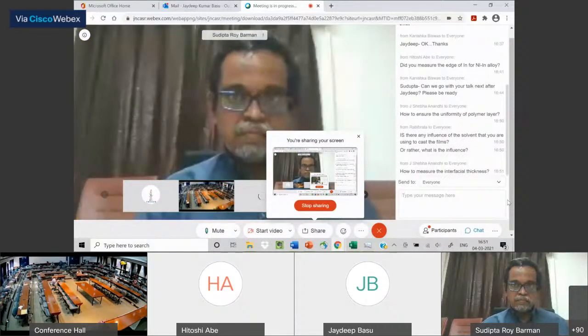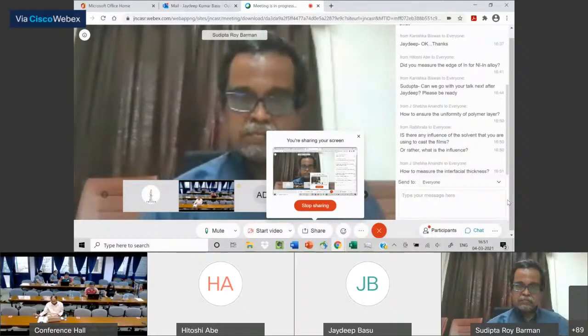Basically you wash out the film. When you wash the film, you see that there is a remaining layer, and that you can easily image with AFM or any other technique. So there are multiple ways you can estimate the presence of this, non-invasive and invasive, both methods. It seems to be fairly uniform as far as I can tell.